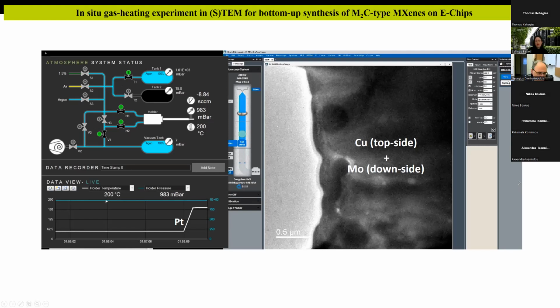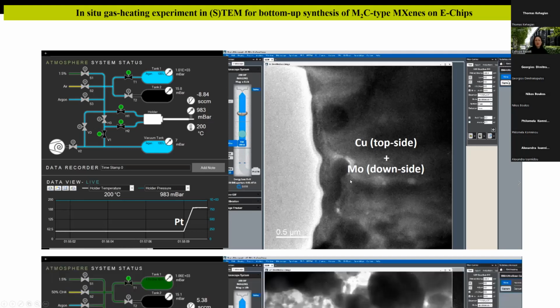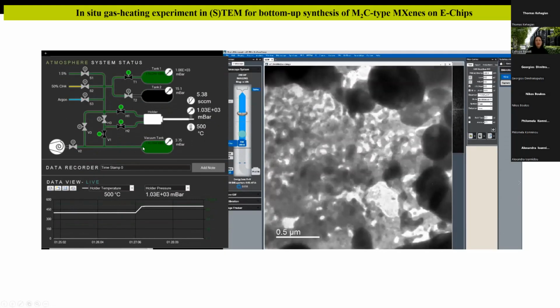We can go up to 1000 degrees. And also, we can change the pressure of the inserted gases. We can go up to 1000 millibars. So you can see here what we see in the beginning, how our sample was before the reaction. And now here we inserted methane and started heating up.